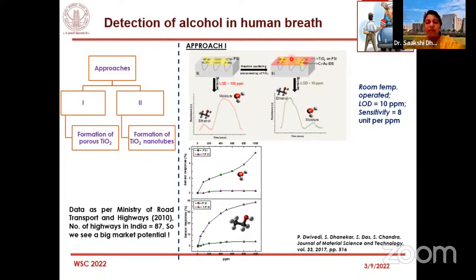So that's what we concluded, that if we use porous silicon with, say, a very thin layer of metal oxide, right? In this case, TiO2, we are able to get a good sensitivity to ethanol, right? But at the same time, if I would expose it to other VOCs, which may also be present in the breath, because breath is not something that is static, right? We have a lot of variables in breath. So then also we could see the change in response, change in the resistance. However, that was lesser. So that became another task now, how can we make it selective? It's really difficult to achieve selectivity with something like metal oxides, right?